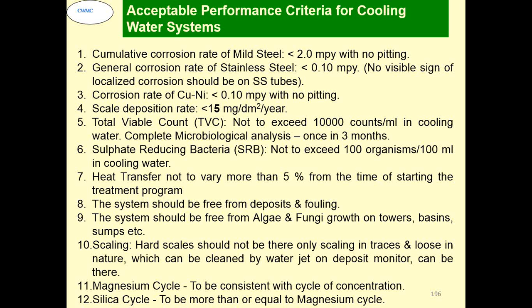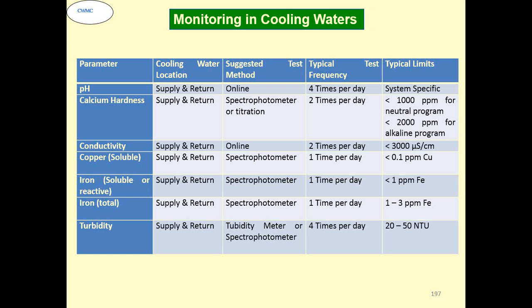Heat transfer not to vary more than 5% from the time of starting the treatment program. System should be free from deposits and fouling. System should be free from algae and fungi growth on towers, basins, sumps, etc. Hard scale should not be there. Only scaling that is loose in nature, which can be cleaned by water jet on the deposit monitor, can be tolerated. Magnesium cycle to be consistent with cycle of concentration. Silica cycle to be more than or equal to magnesium cycle.